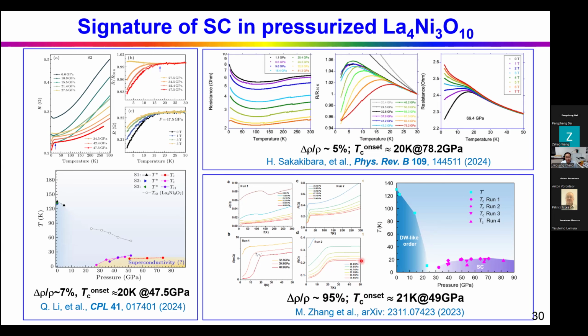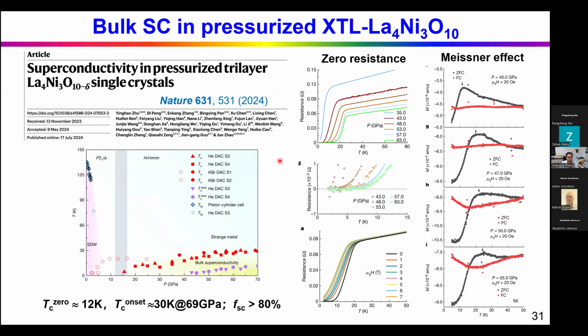But until very recently, Junzhao's group from Fudan University in Shanghai not only observed zero resistivity, but also provided the result of the Meissner effect. So they confirmed bulk superconductivity in these 4-3-10 phases in the single crystal. This is the phase diagram, and the superconducting volume fraction can be as large as 80%.